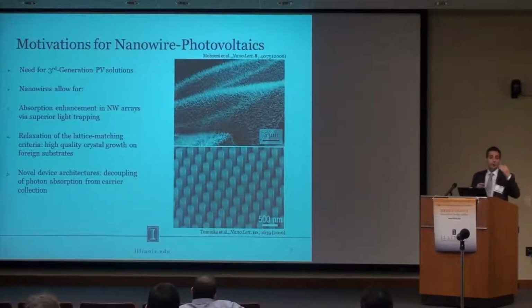In heteroepitaxy, when we grow one material type with a particular lattice constant on another material with a widely different lattice constant, then there's strain associated at that interface. And that strain can lead to dislocations, which present adverse effects for our devices. Now with nanowires, because of the small footprint that they provide, as well as the large surface area to volume ratio, part of that strain can be relaxed along the sidewalls. This allows for a wide degree of bandgap engineering, a combination of dissimilar materials.